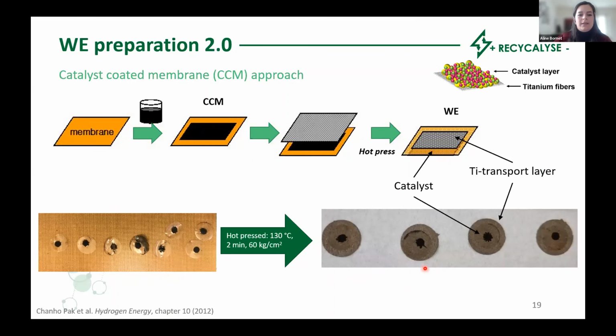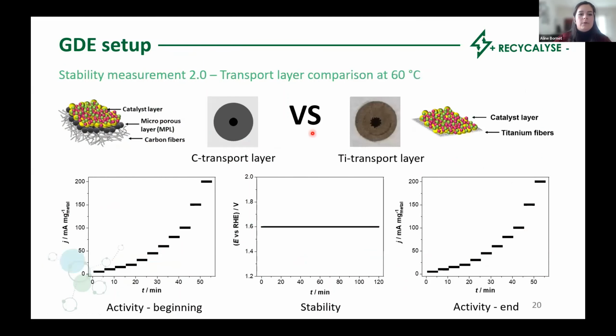Then I used one of these electrodes and I compared it to the carbon transport layer with the same catalyst. And I compared them using the following protocol at 60 degrees. First, the activity was screened as before, so we step the current at different values every 5 minutes. Then comes the stability step, where the potential was held at 1.6 volt for 2 hours. And finally, we repeated the activity step. And in the following slide, I am going to compare the beginning activity to the end activity.